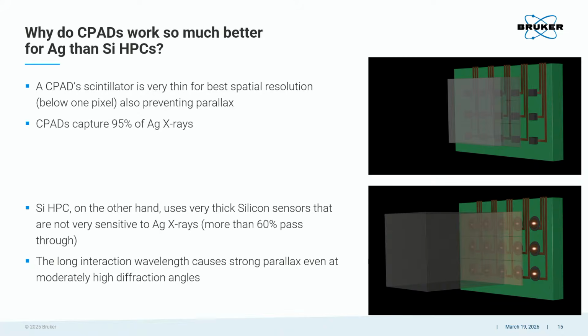If you have an X-ray photon coming in at an angle, and because the absorption efficiency is so low, the interaction with the silicon can happen at any depth. That means if it happens here, I get my cloud and it goes into this pixel. If it happens here, it goes into this pixel. So your signal gets smeared out. As soon as you come in at an oblique angle, not like in marketing material where photons always hit perpendicular, you smear out your signal easily over like 10 pixels.